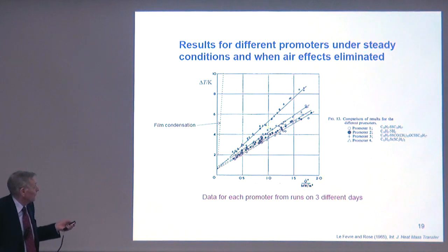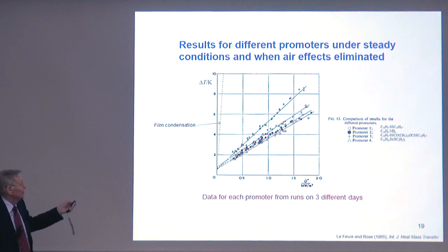You can see clear differences between the promoters. And each set of results was done on 3 different days, so this is very repeatable. Not much difference between these 2 promoters. That one's a little bit worse, and this one is worst of all. But all of this is film condensation. You can see what a big advantage.